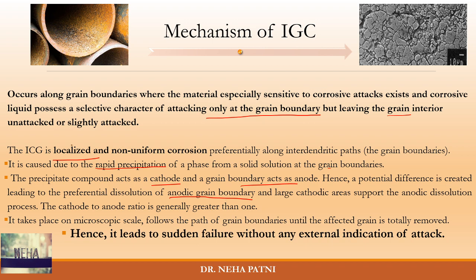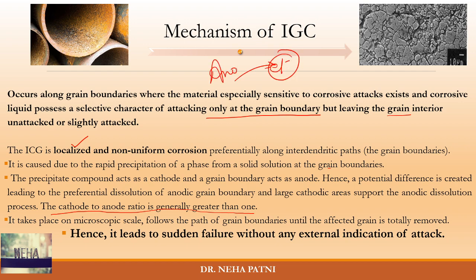This dissolution is the corrosion. It is localized because it intensifies at a particular place. The ratio of areas is important: the anodic area is very small while the cathodic area is large, so the cathode-to-anode ratio is greater than one. When cathodic area is large, the electron requirement increases, and electrons are supplied by oxidation at the anode — so oxidation increases at the anode, resulting in intensified corrosion there.